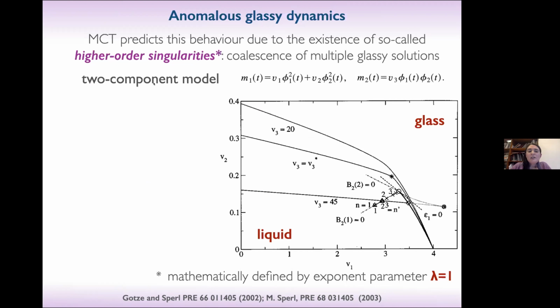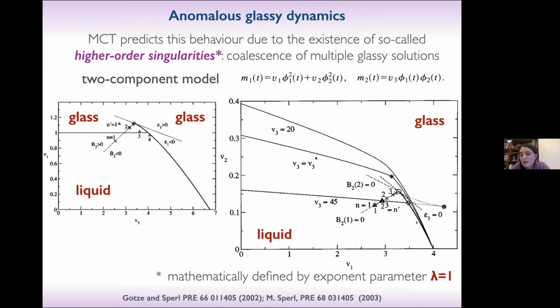And to find it, you need to have a slightly more complex model in which now you have two modes. Before we had only one, so we have M1 and M2, the two functionals that are defined in this way. And basically here you now have three control parameters, V1, V2, and V3. So if I plot the phase diagram at fixed V3, for this particular case of V3, I find something that is basically identical to the one I showed you before. You see that there is a kind of similarity. But then now you have the possibility also to change V3.